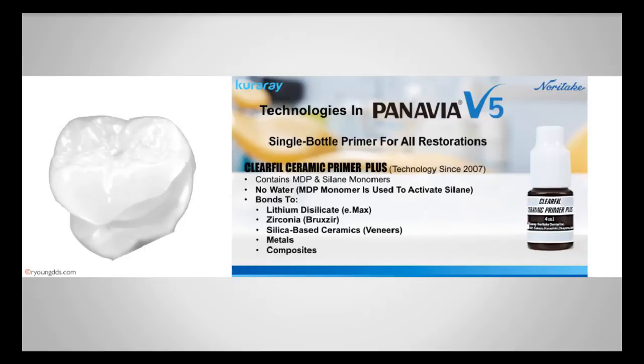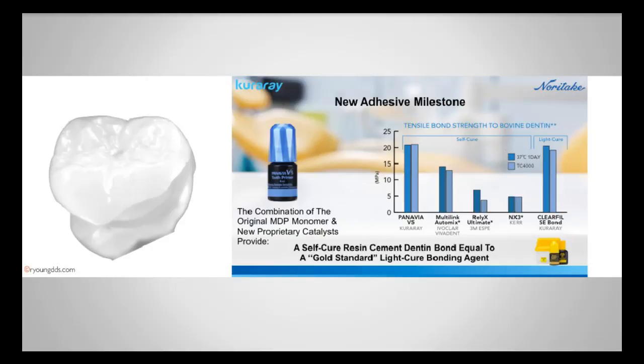We don't have time to talk about MDP monomers, but certainly Kuraray is known for their MDP monomer. The combination, the new adhesive, is that you have the MDP monomer in the adhesive as well. So it's in the primer for the metal or the restoration, and it's also in the adhesive for the tooth. It's an adhesive that meets right up with Clearfil SE Bond in its strengths. So your tensile bond strengths of the light-cure SE Bond and the Panavia V5, a self-cure resin cement with a dentin bond, are equal to a gold standard light-cure bonding agent. So it's a wonderful primer.